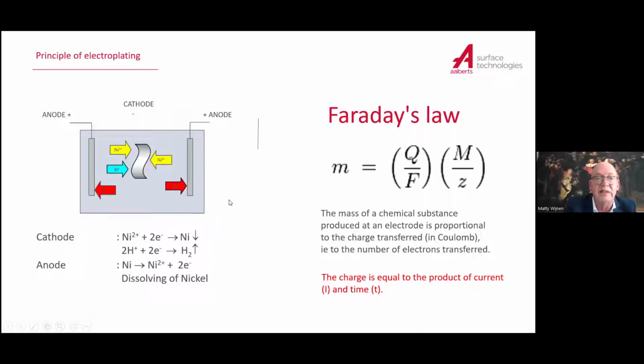Here is a little bit written to show what's happening in a nickel bath, just to make it clearer. Nickel, which is charged positively, the nickel ions move to the cathode, hydrogen ions move to the cathode, and the chloride anions, which are also there as ions, move to the anode. That means that on the cathode you have nickel and some hydrogen development, and on the anode,